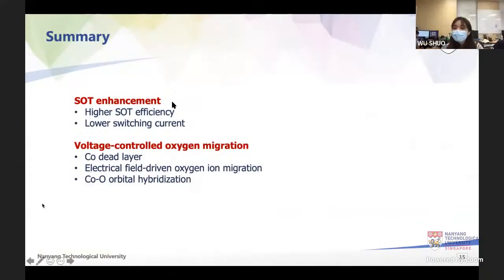So in summary, we experimentally demonstrate the enhancement of both damping-like torque and SOT efficiency with HFO capping, and the oxide layer causes the oxidation of the cobalt, which contributes to the interfacial Rashba effect. And we also apply different gate voltage to investigate how the electric field will affect the SOT efficiency.